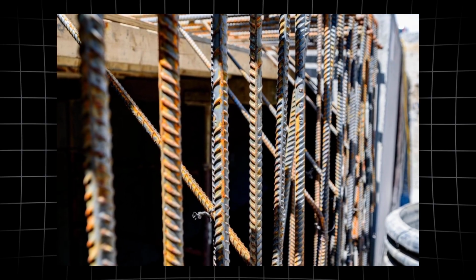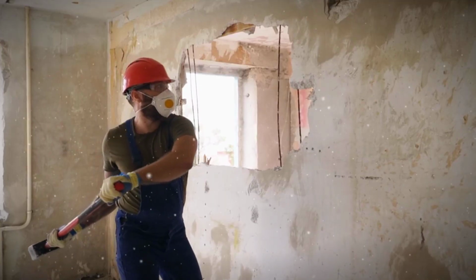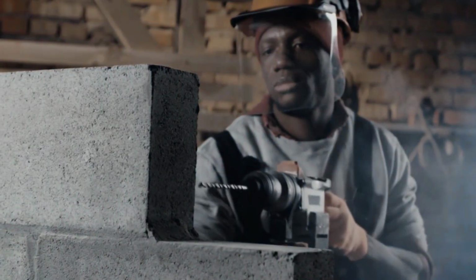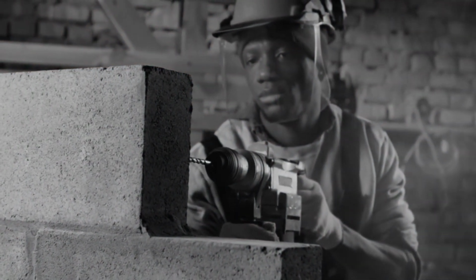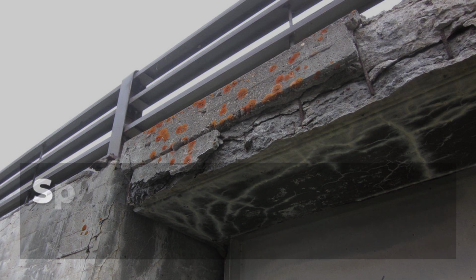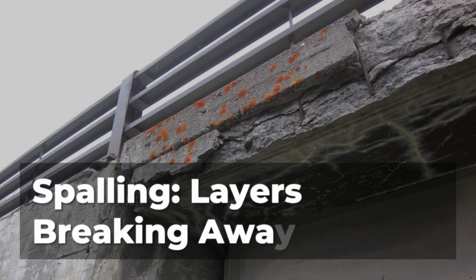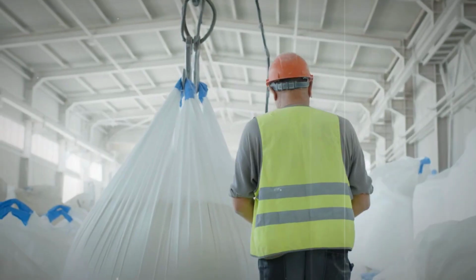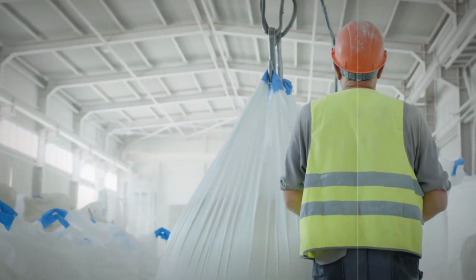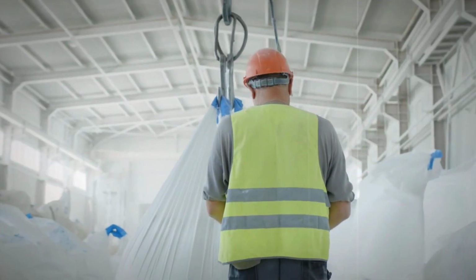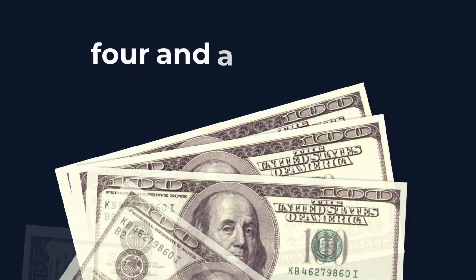As rust forms, it expands to up to 6 times the volume of the original steel. This rapid internal expansion exerts immense tensile pressure on the surrounding concrete, cracking it from the inside out and causing the outer layers to break away in a process known as spalling. This continuous cycle of physical degradation lies at the heart of the $4.5 trillion global infrastructure maintenance burden. Repairing these compromised structures is not a permanent fix, but a temporary delay.